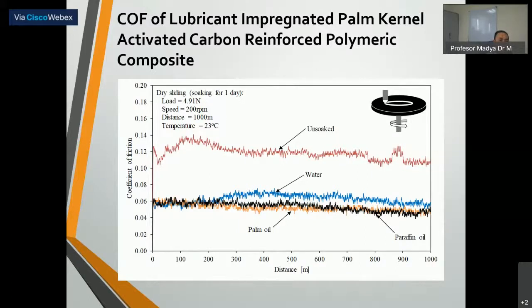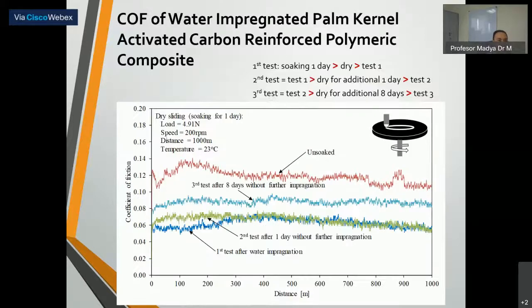Okay, here we soak the composite for 1 day. After we soak for 1 day, we take out the sample, dry the sample, and then we test. This is the coefficient of friction of the water-impregnated sample. Actually, this is the first test. We soak for 1 day, dry, and then test. After test 1, we dry again for an additional 1 day without any impregnation, and then we test. For test 3, we dry again for an additional 8 days, and then we test again. So this is the result.